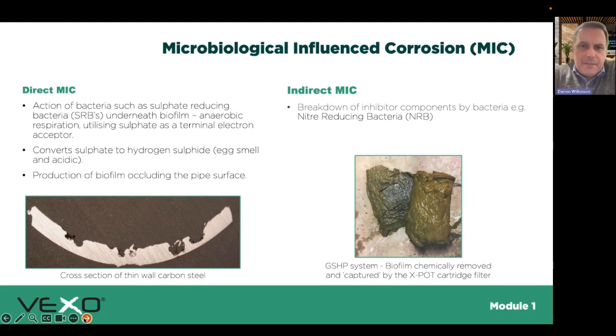I think this is going to start showing its head more so now we move to much lower operating temperatures, but this is another form of corrosion called microbiologically influenced corrosion, MIC. So essentially we can have bacteria, if you imagine the fresh water that makes up to the closed loop system, pipework can be sitting there for some time before there's a demand on the system that says it's only topping up. And in that time, mains water will have a very low level of total viable count. It has a low level of bacteria in the water. Typically, we like to think, certainly not any pathogenic concerns, but certainly low levels of bacteria in the water. And of course, if it sits there idle and it's got the right temperature, it's going to proliferate and you're going to have bacteria. So every time the system makes up, you run the risk of giving it a flu almost,